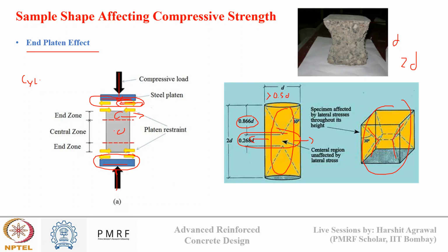So that's why in cylinder we observe a lower strength, due to the presence of this weak plane in between, where there is no resistance offered by the platen effect. And in cube there is the entire cross section under the end platen effect, and that's why it has a slightly higher strength compared to cylinder.